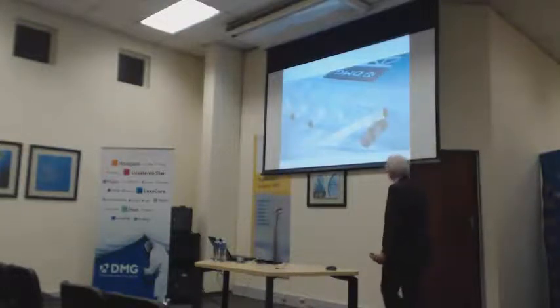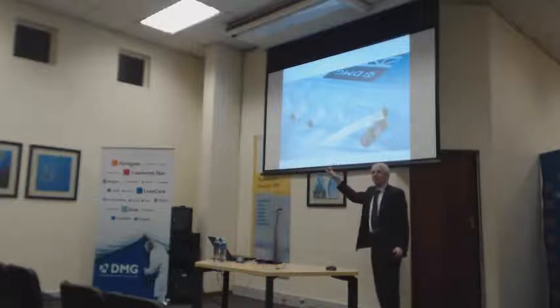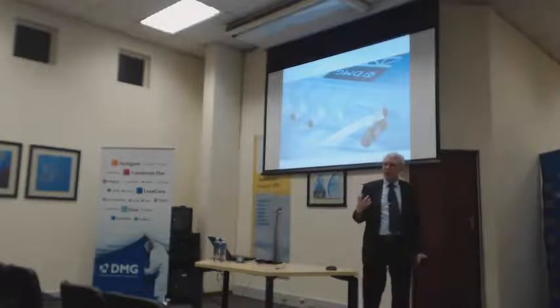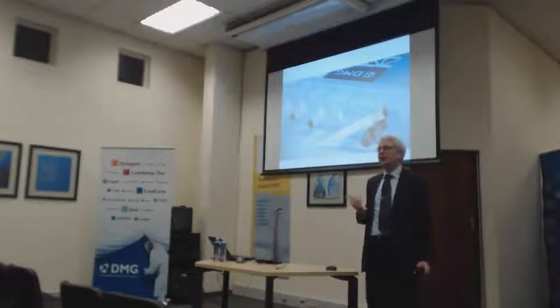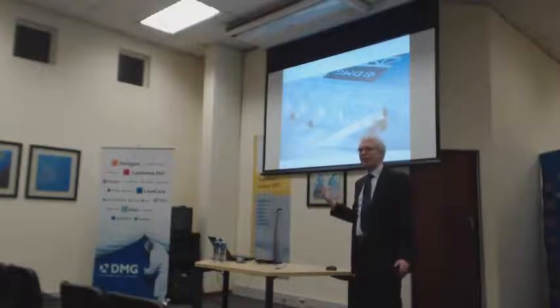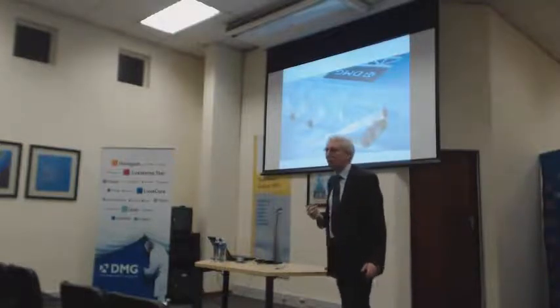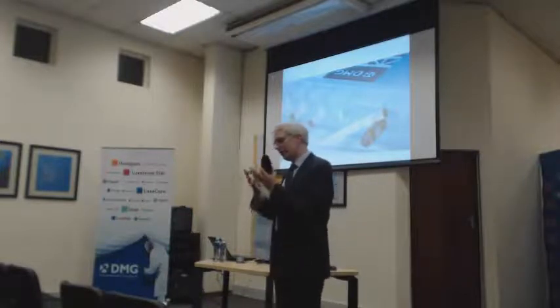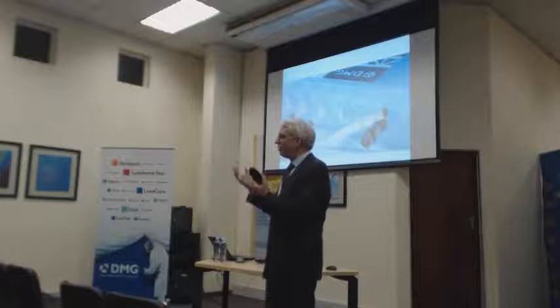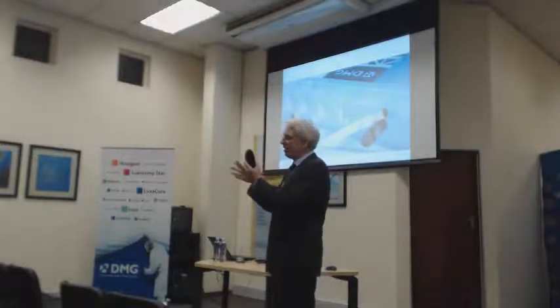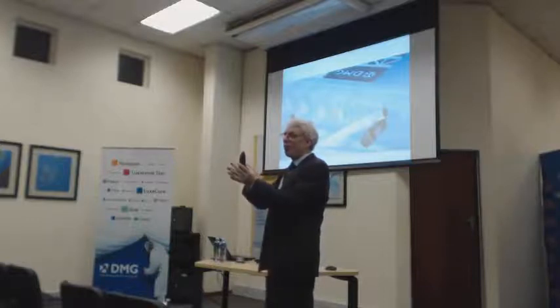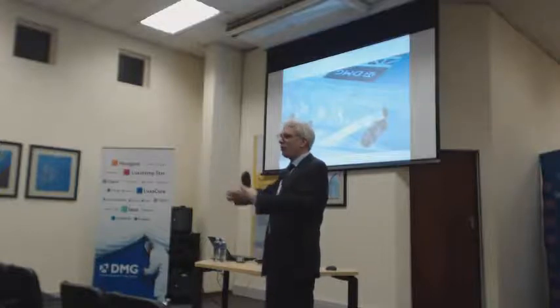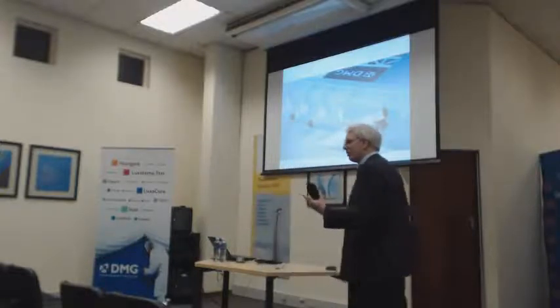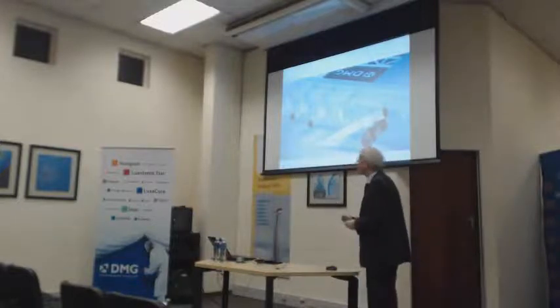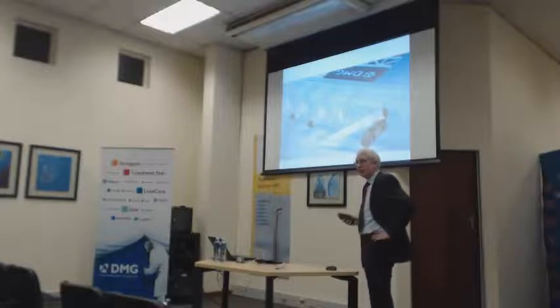To ensure that you get this, we use a tapered post. And you can again say what you want about tapered posts. It's also a decision about your cement at that stage. Say you have a phosphate cement and you want to use it with a tapered post. This is not such a good idea because the phosphate cement is not inherently very strong. So when you place a tapered post like this, it can crush the cement, and then you get what's called a wedging effect. It's like putting a wedge into the wood and then cracking that tree. It's the same thing. So you're running a high risk of fracturing the root with this. But if you're using a resin cement, that is strong enough. Wedging doesn't happen. Everything is cool.